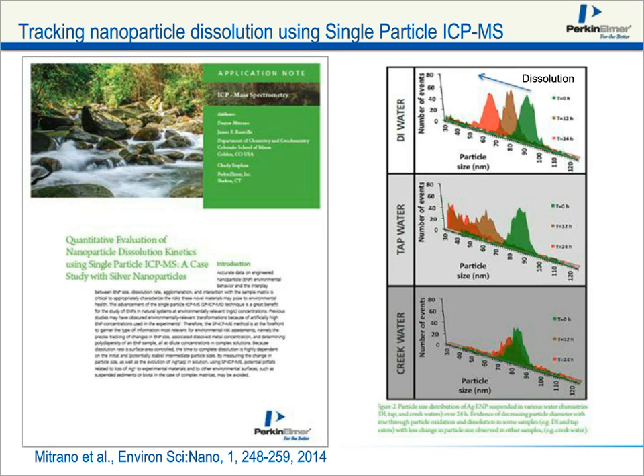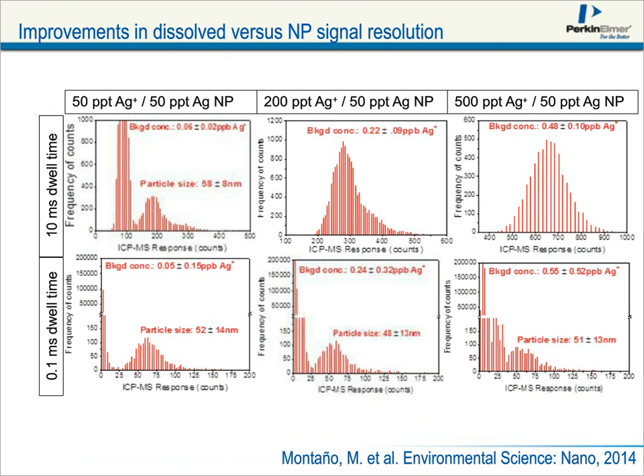Kevin was quite successful in his ion exchange approach to removing that background, but another thing we can note is that as we reduce our dwell times, the contribution of the background relative to the signal can be reduced. So in this particular slide, we show a 10 millisecond dwell time, something we started out working with when we first started with single particle. We've now reduced it to 0.1 millisecond dwell time. Notice that background peak on the left graph. It's centered somewhere around 100 counts or so. Of course, if I drop the dwell time by a factor of 100, I drop my background down by a factor of 100. So now my background's on the order of 1 or 2 counts.